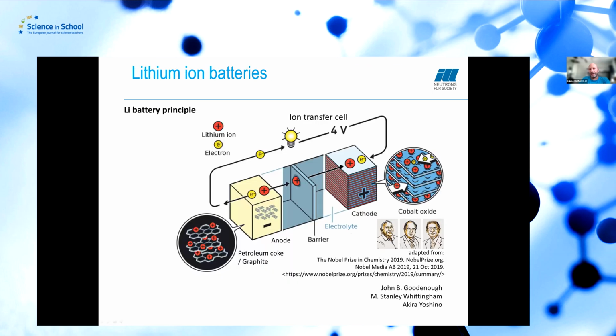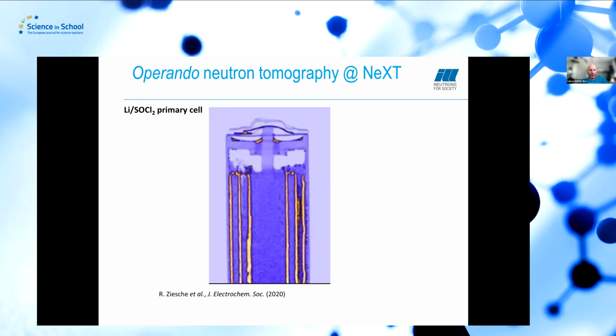Sorry, that was a bit too fast. And at the cathode, the same principle applies again, that the ion gets intercalated into this NMC, for instance, or cobalt oxide cathode material. So for the intercalation, you generally create stresses and volume expansion, and that makes the material work, expanding and contracting over different charging and discharging cycles. I will show you what you can do now here with a working cell.